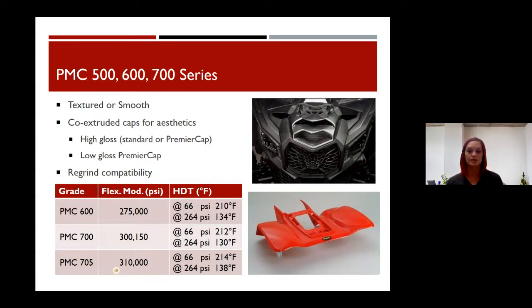So you can see how the flex mod moves. Your PMC 600 is a standard, looking at around 275,000 PSI flex mod, HDT around 210. PMC 700 is probably one of the most popular grades. That's the high melt strength. You get a couple degrees on HDT, but you really gain about 25,000 PSI on flex mod. And then PMC 705, we call our ultra high melt strength product. 310,000 PSI on the flex mod. It's really for those parts that need a little more stiffness, a little more sag strength, that need to take a deeper draw or some features.